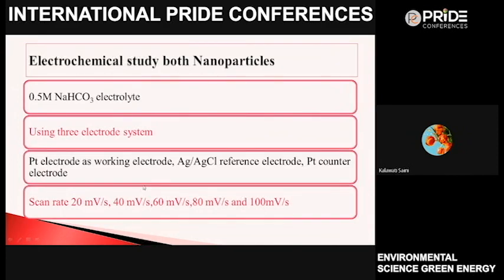The electrochemical study has been done using the cyclic voltammetry technique, where 0.5 molar sodium bicarbonate is used as a supporting electrolyte. A 3 electrode system has been used. Platinum is used as the working electrode. The synthesized green particles are drop casted on platinum, which works as the working electrode, Ag/AgCl as the reference, and a platinum counter electrode. And the different scan rates at which the cyclic voltammograms were scanned.